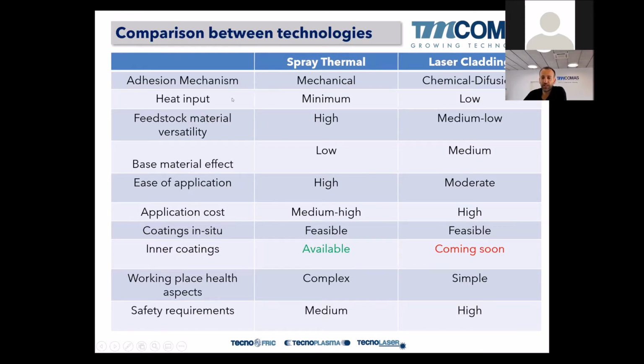So the adhesion mechanism in thermal spray is mechanical, while in laser cladding it is chemical. It's a real weld, so we have some diffusion welding. Heat input in thermal spray technologies is minimum because the flames are produced in the gun, not over the substrate, so the heat input is minimum, while in laser cladding it is low, the lowest of all the welding technologies.